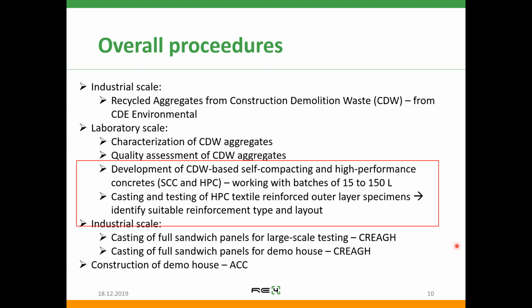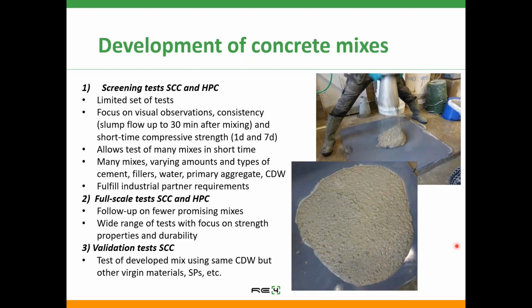So this is what I'm going to focus on in my presentation, the laboratory work in between these industrial scale works. Starting with the concrete, I will not say so much about aggregate characterization and assessment, because that will be the topic of a later webinar. But after your characterization, you have your CDW, you know its properties compared to virgin materials, and we use this to adapt and optimize mixes, both for self-compacting concrete and for high-performance concrete, starting with screening tests on small batches, like 15 liters, to look at workability and short time properties, like compressive strength after 1 day and 7 days.